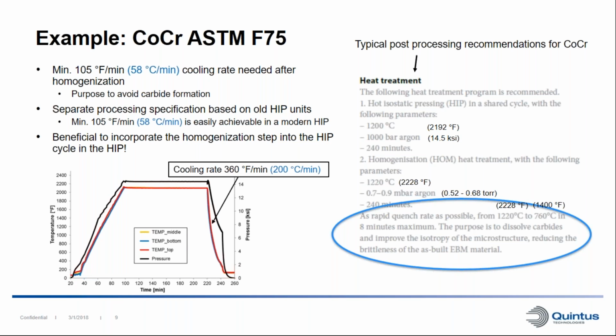And as we can see here on the left, in this way, we don't have to heat up the material to above 1200 degrees twice. We don't have to spend 8 hours at elevated temperature, just 4 hours. And we don't need 2 equipments to perform these 2 different steps. We can do everything in the HIP.